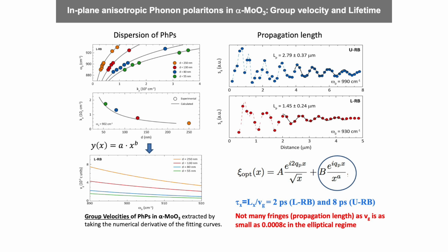So depending on the application, and this is the key point, either lifetime is good, or it is gamma to the minus 1, I mean the quality factor, how many wavelengths. If you want to make an interferometer, or an optical device where you want to move this wave over a very long distance, you need a high quality factor. But if you want to make cavities or light-matter interactions with sensing and so on, lifetime matters more. Okay? This is a point because I think sometimes in the community it's mixed. People think that talking about this, the gamma to the minus 1, is enough. Others, we don't talk much about gamma to the minus 1.